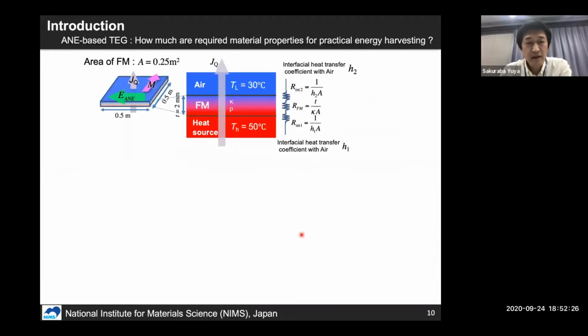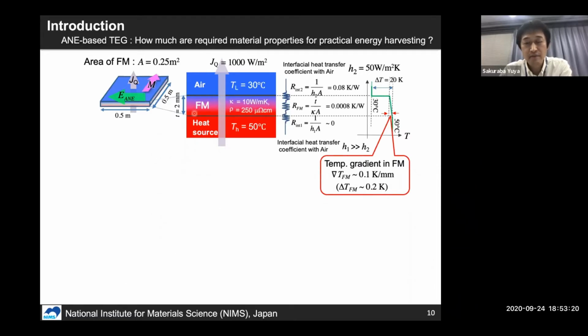In order to understand how much thermal power is required to realize anomalous Nernst effect-based energy harvesting, we performed one simple simulation. For energy harvesting, we cannot use a very high temperature heat source, so usually the heat source must have a temperature around room temperature. Here we consider a heat source having a temperature of 50 degrees C, and the heat bath is air at a temperature of 30 degrees C. In this simulation, we insert a magnetic material of 50 centimeter by 50 centimeter area, and the thickness is 2 millimeter. And in order to calculate the obtainable anomalous Nernst electric power, we put in typical thermal conductivity and resistivity for this magnetic material.